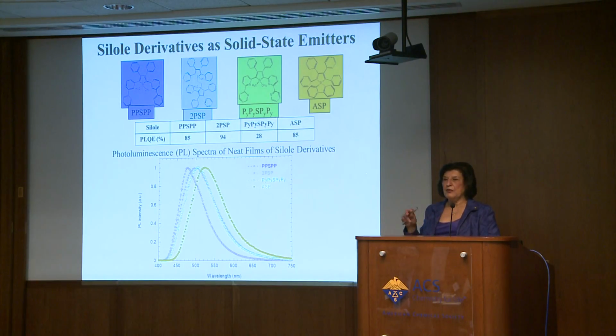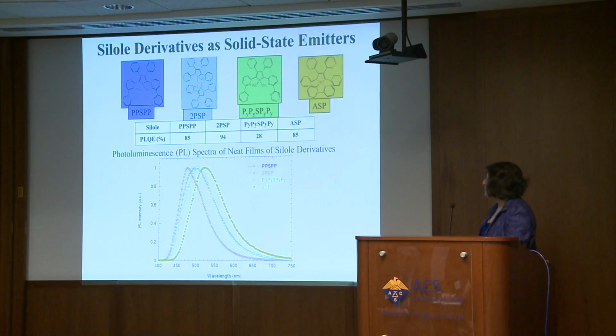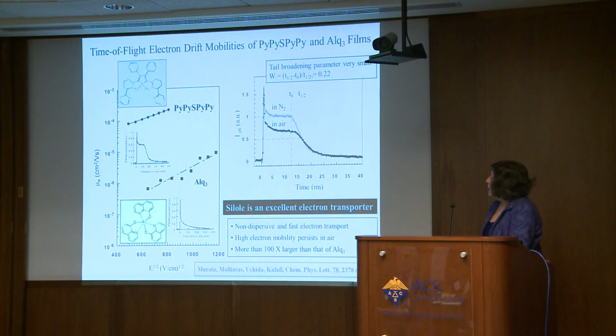Usually the most highly efficient emitter is a single molecule. When you form a dimer and trimer and then grow the molecule, the emission goes down and down. But in this case, it's the opposite. These materials have a fluorescence quantum yield that can reach up to unity. We also found that they are very good carrier transporters. They transport electrons very efficiently.